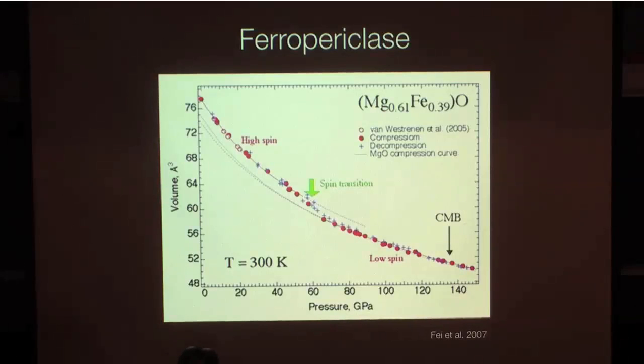How dramatic is that, right? It doesn't collapse, but we love to dramatize what we found. So now, simple question to ask. Bulk modulus, before and after spin transition, yes, it's probably the same as the magnesium end member because bulk modulus is a slope in this plot. What happens in this interval where you have a spin transition?